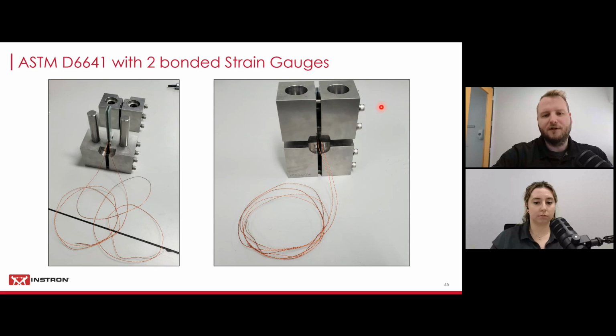And then you need to make sure that you use the right torque, which again is recommended in the standard. For the first test that I ran to failure, I did use the recommendation in the standard. I think it was between 2.5 and 3 Newton meters, which worked out perfectly, as you've seen in my test. So I got the right failure mode and I did not get any end crushing. So that is where you would want to make adjustments if you don't get the right failure modes or your ends crush.